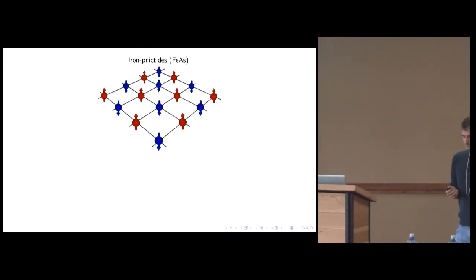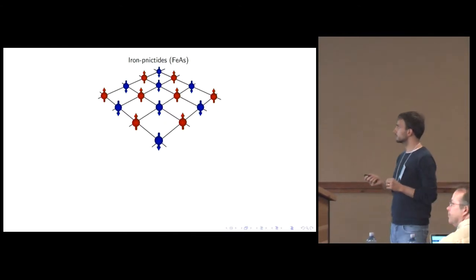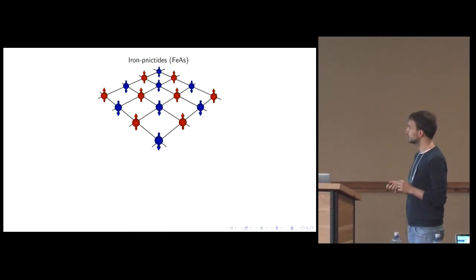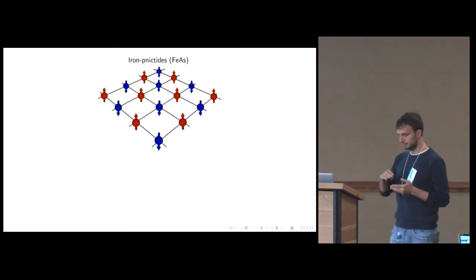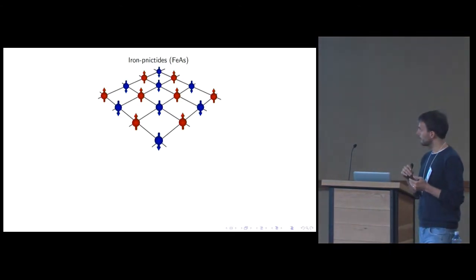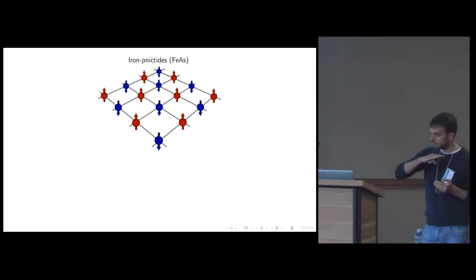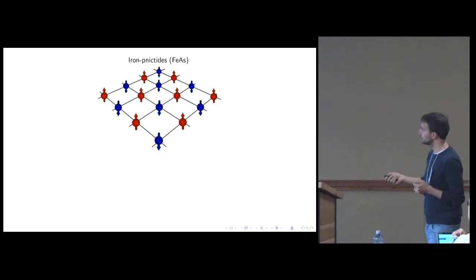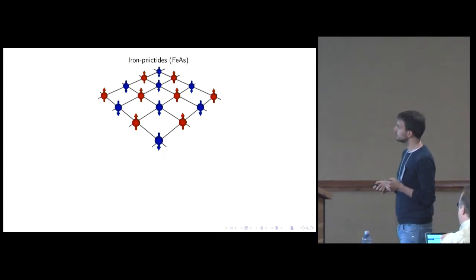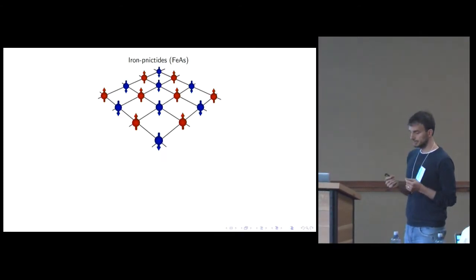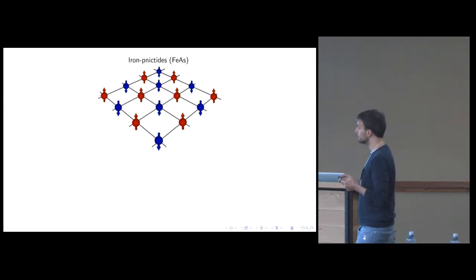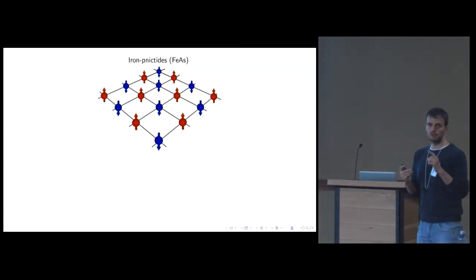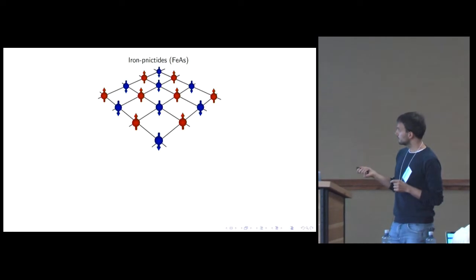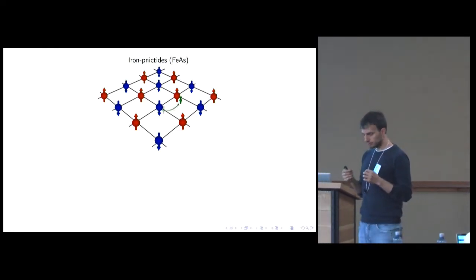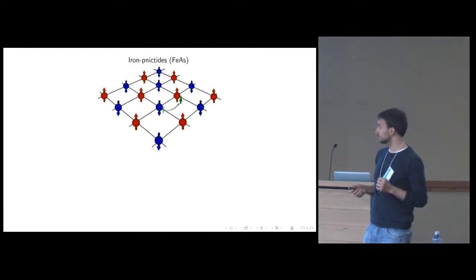Okay, take for instance the example of the iron-pnictides family. These materials are essentially layered. You have layers of iron atoms that are usually arranged in a two-dimensional square lattice. And these irons have a magnetic moment, and naturally they tend to anti-align between each other, as I represent here. The issue is that we also have some electrons flowing around in the system.